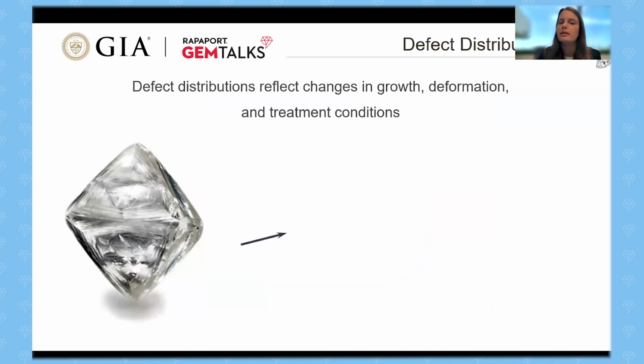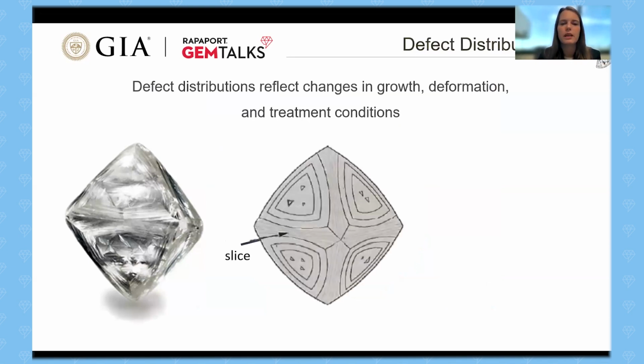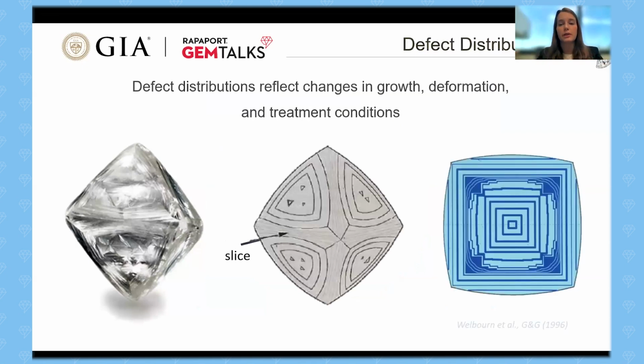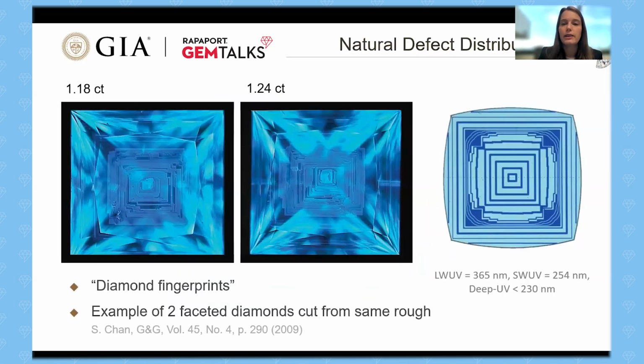So here we have our natural diamond octahedron rough crystal. If we were to slice through its belly here, we would see essentially a series of growth rings. These rings for the vast majority of diamonds are going to be octahedral, which gives you a sort of square-shaped pattern in the center, but there can be a range of different, very clearly natural patterns that with practice you could recognize. So here you have an example of a natural diamond. In fact, these are really acting as fingerprints. These are two separate diamonds that were submitted to GIA around the same time, and we were able to match these patterns and actually say that these came from the same rough. So they are truly, truly intrinsic to the stone.